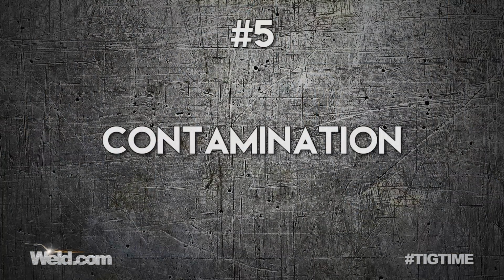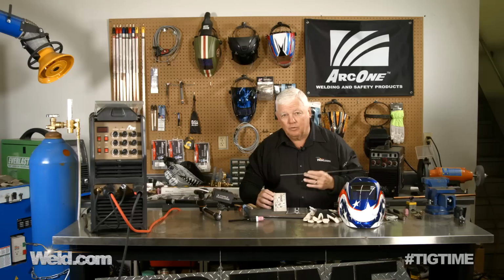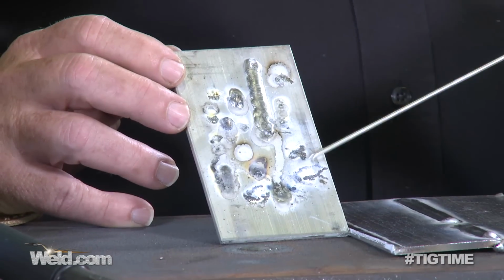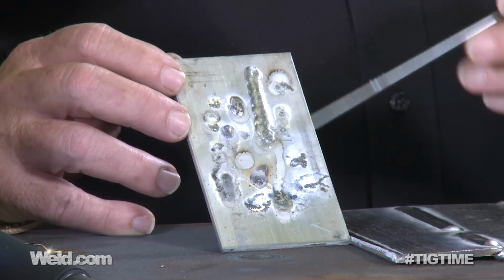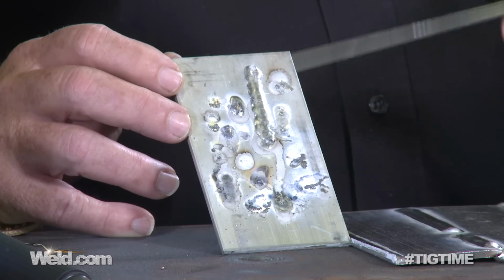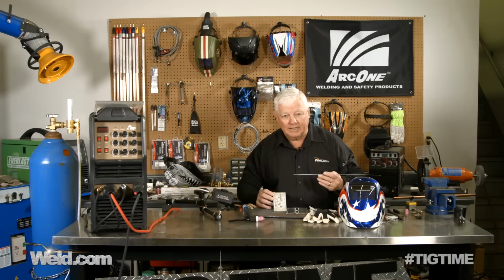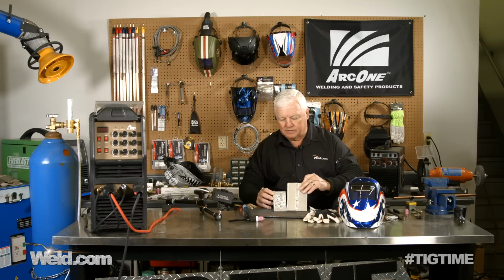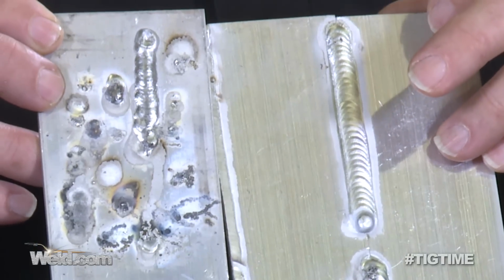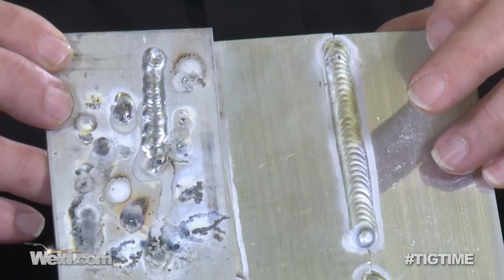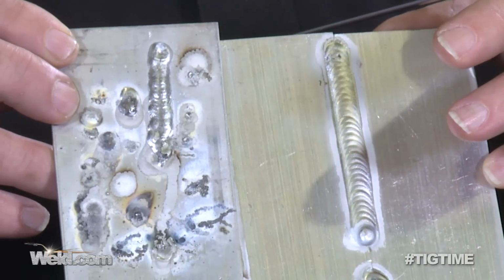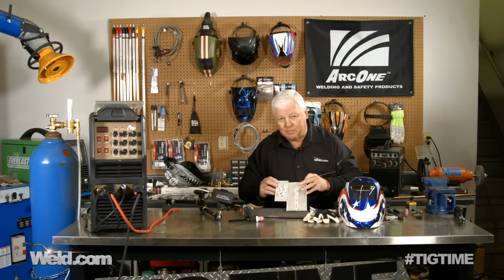Okay, this is another helpful hint. This happens quite frequently when welding aluminum, specifically aluminum, because it's so sensitive to tungsten contamination. Are you having this kind of a problem? You're lighting the arc and you're getting little globulars and you get black and soot and all that, and your puddle is just not flowing out very nicely or clean. Just one little change can help that. And in many cases, you don't even know it's happening, because in aluminum, you'll be welding along and dabbing your filler and you'll get tungsten contamination.